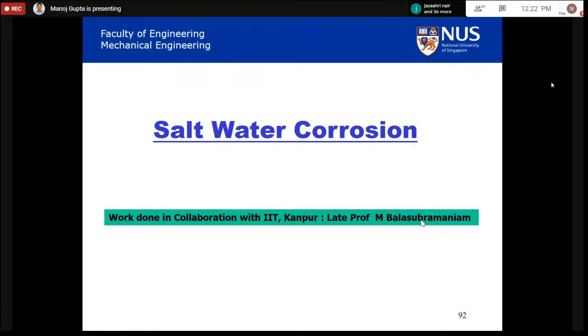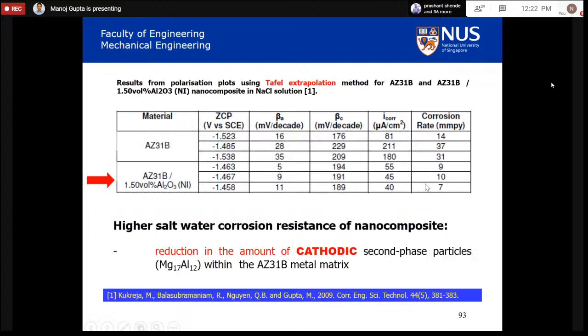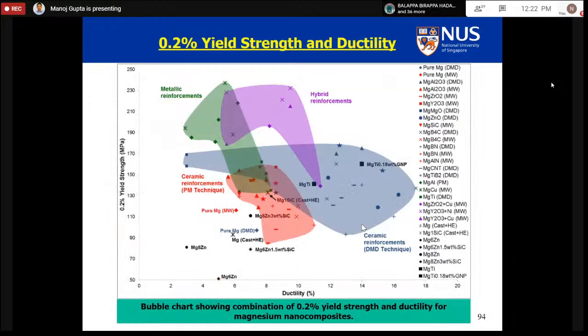the steels. We also did the corrosion investigation in the wet condition with collaboration with late Professor Balasubramaniam in IIT Kanpur. And he found that the wet corrosion susceptibility of the nanocomposite reduced to 1/3 if you put the nano reinforcement by Al2O3, and he attributed that to the reduction in the cathodic phases, which are responsible for enhanced corrosion.